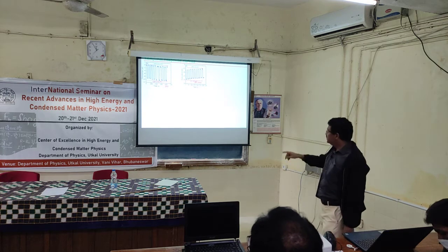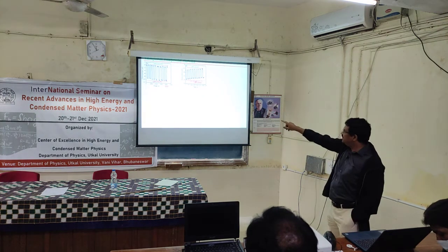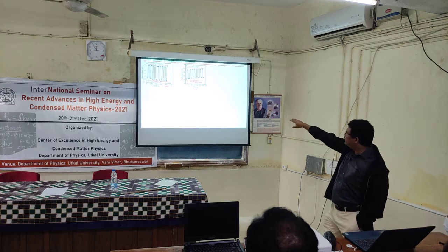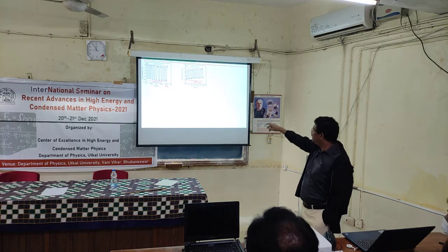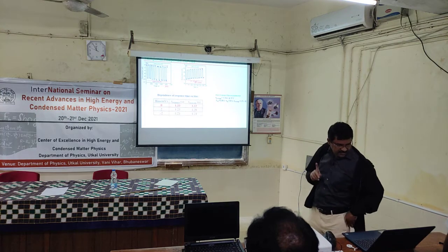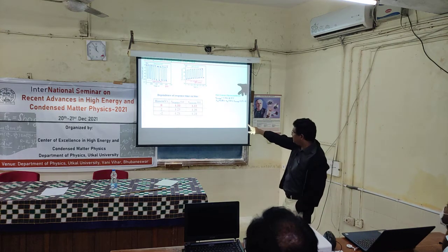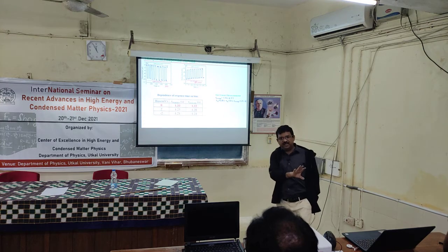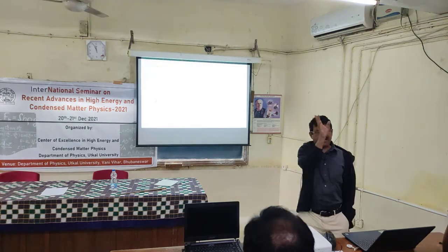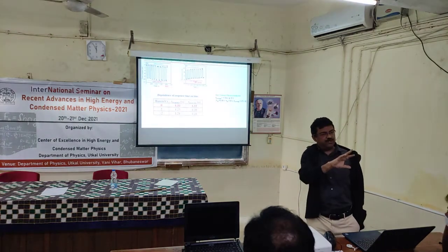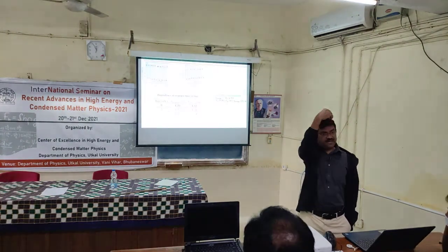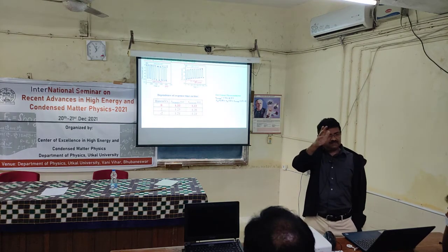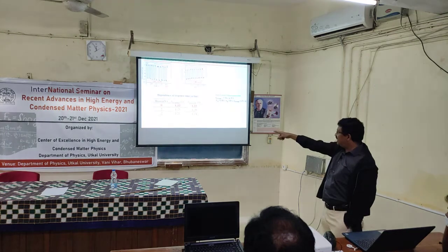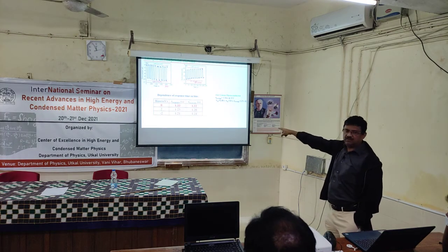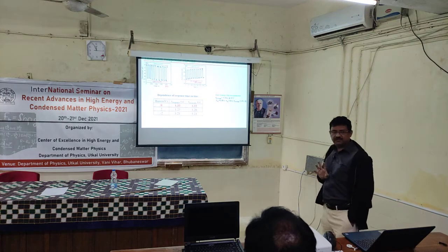And this is how the temporal response curve looks like, again at zero bias. Okay, and this is at minus 2 millivolt. But overall, the important thing is that in this case, the response and recovery time is very fast. I mean, at least faster than the linear device. In that case, depending on the bias, if you apply 5 volt, it is 7 seconds. If you apply 10 volt, it is 2.5 or 3 seconds. But here, without any bias, as you see here, you can have 1.33 and 1.2 seconds. Okay, so a little bit faster than the previous one.